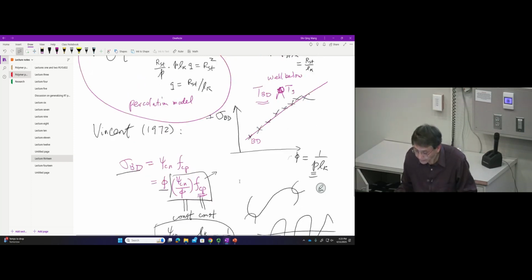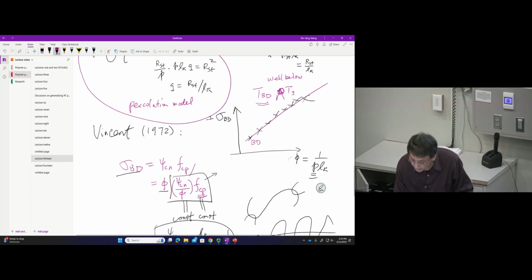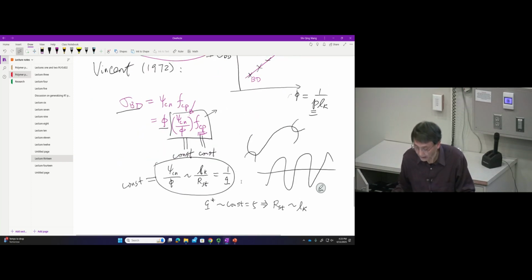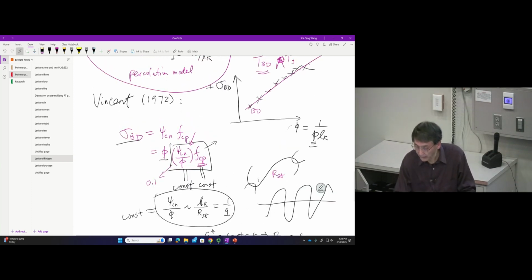Moreover, if you can plug in some reasonable numbers for the size of the strand, you make a guess, something perhaps reasonable, roughly speaking about a tenth of it, then you can compare with the data and suggest what this F would be. Right? So that was what was done 10 years ago.